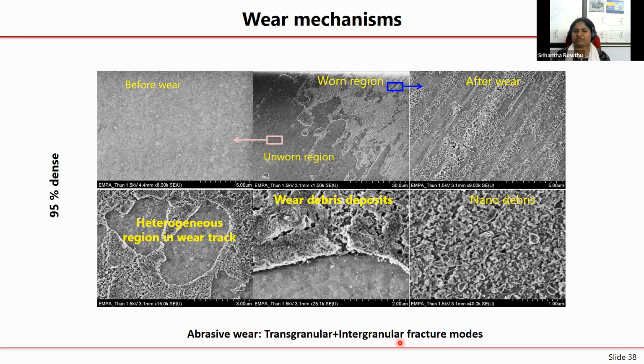So for the 95 and 99.5% dense specimens, typically the debris were having much smaller sizes as compared to the initial grain sizes. So that can actually explain that the grains have fractured, so the crack has propagated through the grain. That is, it is predominantly transgranular fracture for the highly dense specimens. So during this, not only has crack propagation happened, but in many places there is a tribosintering phenomenon that has happened also.